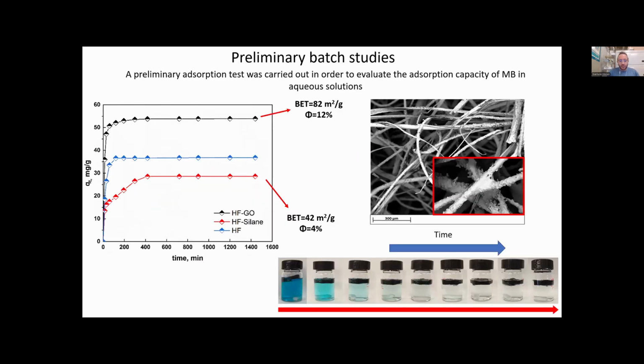Then a preliminary batch study was carried out to compare the adsorption of the graphene oxide modified hemp fibers with the pristine ones. Here you can observe a noticeable improvement in adsorption capacity, which can be ascribed even in this case to the increase in specific surface area, increase in porosity, and the high availability of adsorption sites on the surface of hemp fibers due to the presence of negative groups of graphene oxide. Even in this case, in less than 24 hours, this material is able to decolorize a 50 ppm methylene blue initial solution, and you can observe the colorimetric change on the bottom side of the solution from dark blue to transparent water.